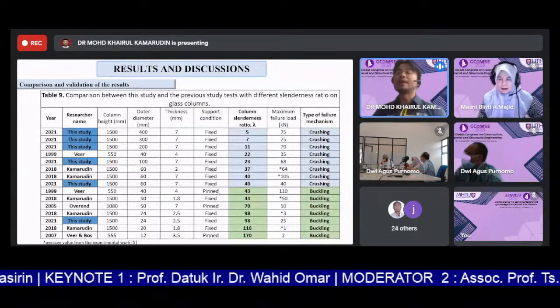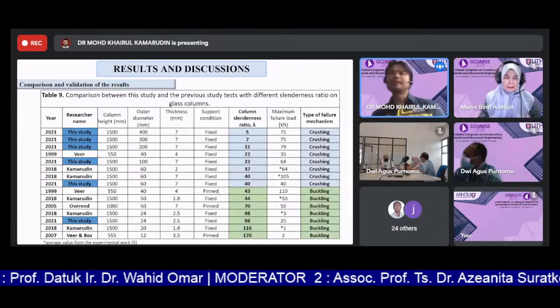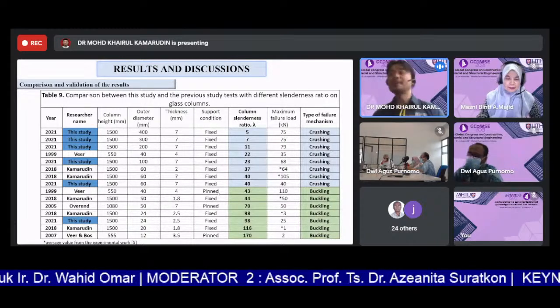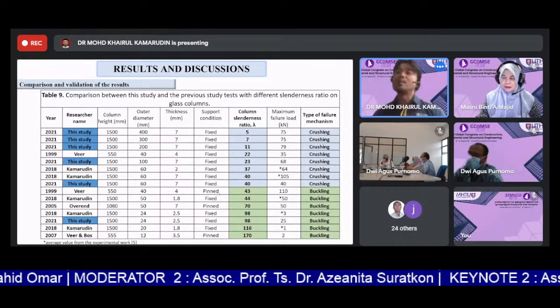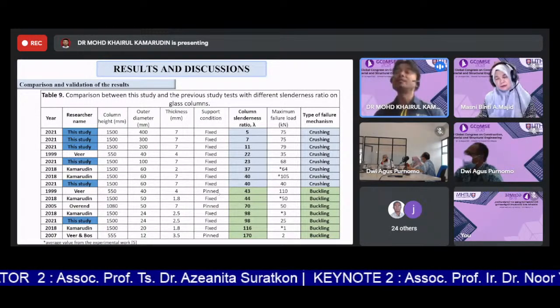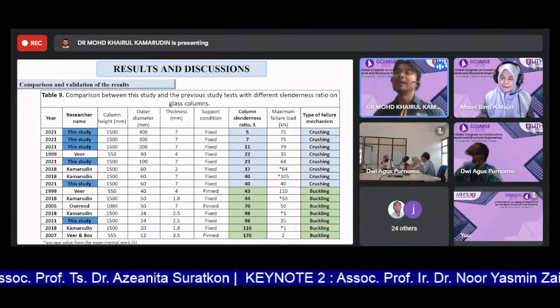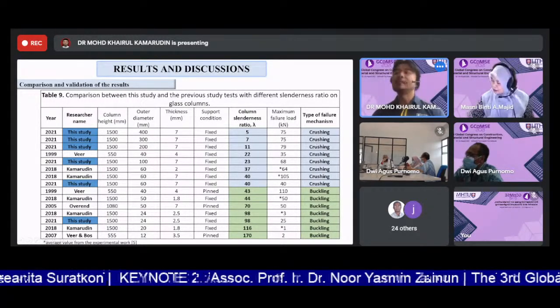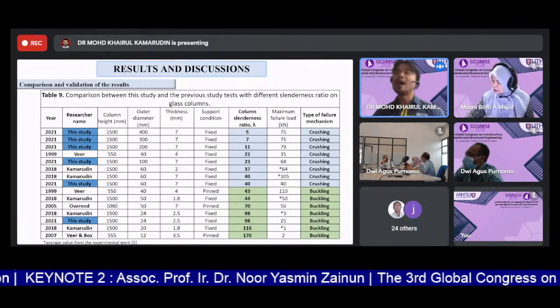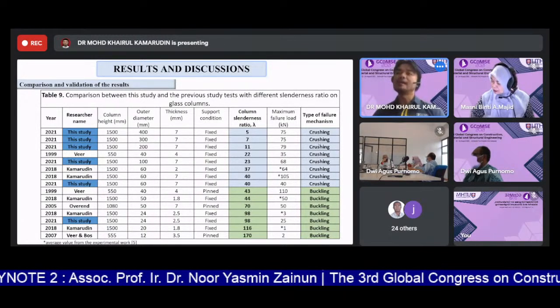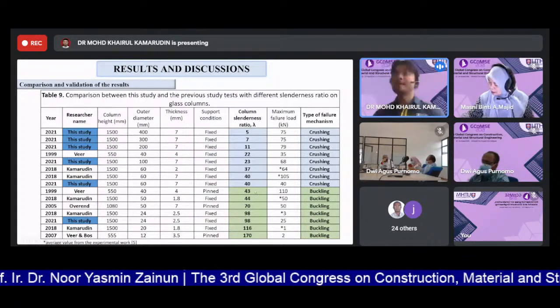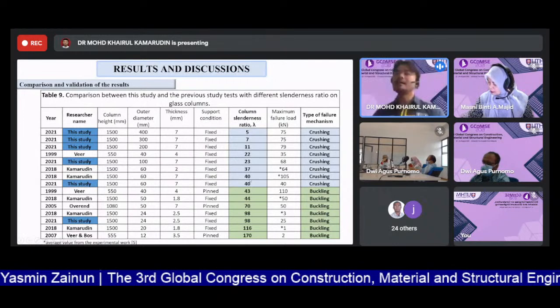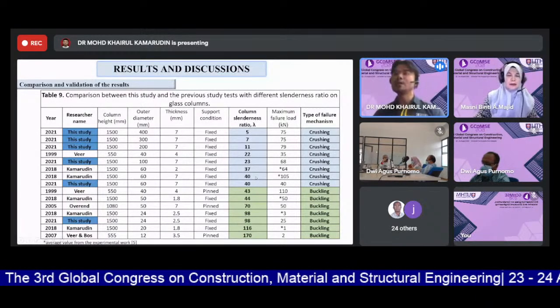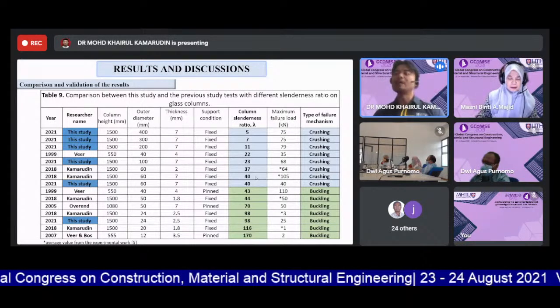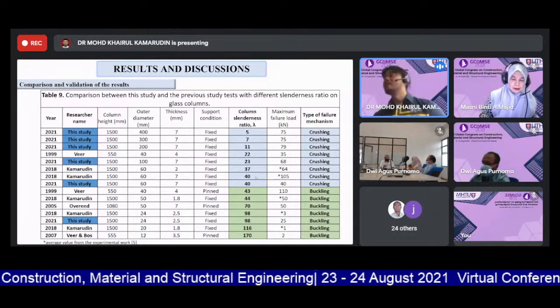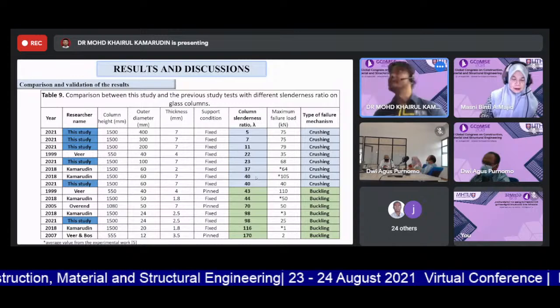So in this table, we show that, as I mentioned just now, when we have variations of slenderness ratio, we managed to capture a significant type of failure mechanism that marks how the glass column will collapse, either in terms of crushing or buckling. So in this case, we still managed to secure that this 40 slenderness ratio should be the benchmark to distinguish how a glass column should collapse.